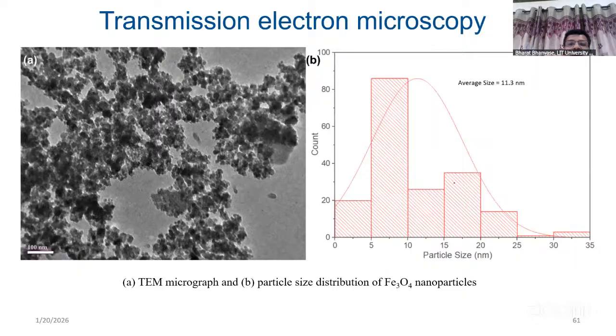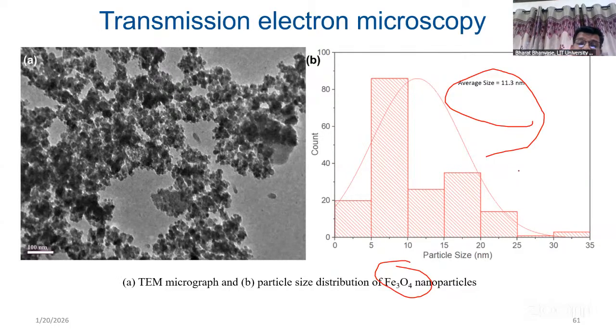So this is the TEM analysis. You can check, this is for Fe3O4 nanoparticles, right? You can observe the particles are less than 50 nanometers. Particularly if you see the histogram, the average particle size what we observe, that is 11.3 nanometers, which is produced in this. This is for Fe3O4 nanoparticles.